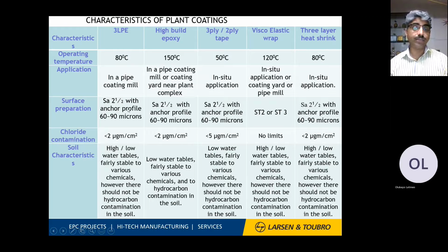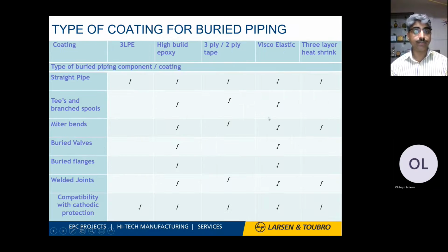SA 2.5 is a Swedish standard. It normally gives 60 to 90 micron roughness over the surface, by which paint can adhere to the surface profile. So it gives you very good locking for the primer and subsequent coats. Chloride range is always, of course, a challenge, but for viscoelastic wrap tape, there is no limitation. So you can apply this in the field, and it has good barrier properties at 120-degree temperature.